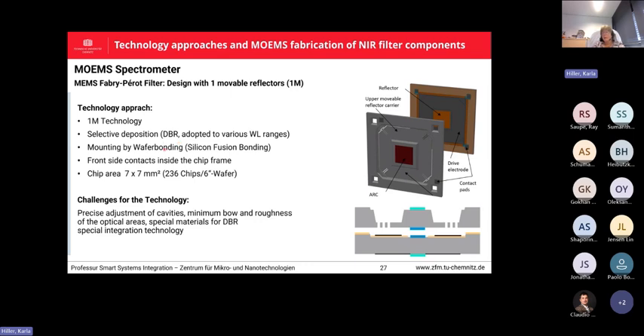And we want to mount the wafers together by silicon fusion bonding, because this SU8 has some not ideal characteristics over temperature and over time. So that's why we wanted to use the direct mounting of the surfaces together. So this means, on the other hand, we need a precise adjustment, in this case using etch processes to establish the optical cavities. Then bow and roughness, this I show also in detail, are critical because we want to have parallel optical reflectors. And if we use the selective deposition, this I also show in the next slide, then we have a special integration technology to enable this.